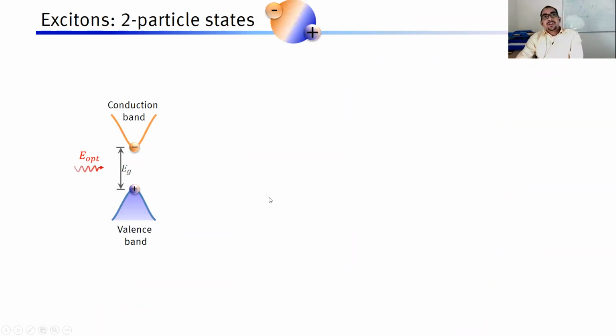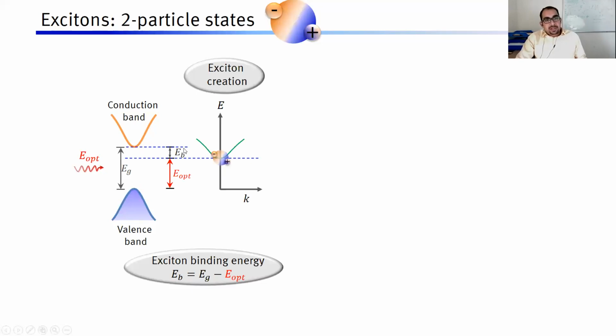Okay. However, this was just without Coulomb interaction, because now if we create electron hole pairs in a semiconductor, we have Coulomb interaction, right? So this Coulomb interaction actually leads to the formation of hydrogen atom-like species in a semiconductor, and these are called excitons. In fact, the spectrum of these excitons we would also expect to be similar to that of a hydrogen atom. Now we shine a photon again, we create these electron hole pairs, and they are bound by Coulomb interaction with an energy equal to EB.